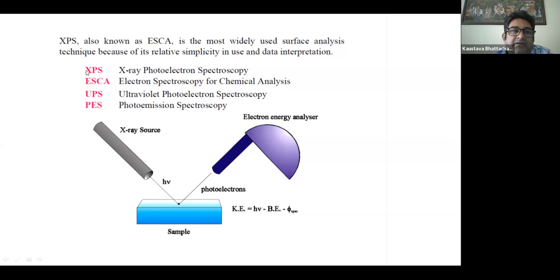These two together, that is X-ray photoelectron spectroscopy and ultraviolet photoelectron spectroscopy, are called photoemission spectroscopy, or PES. So basically, to make the long story short, we have an X-ray source which falls on the sample. It ejects a photoelectron. The kinetic energy of this photoelectron is measured by the detector, and this kinetic energy is correlated with the binding energy of the system. So we get the binding energy of this system.